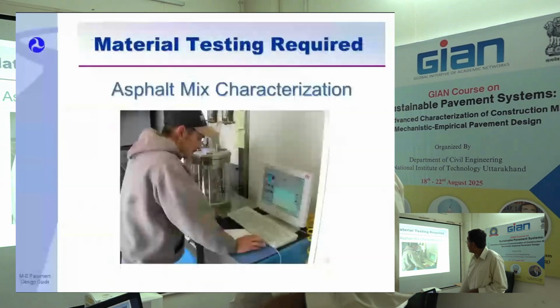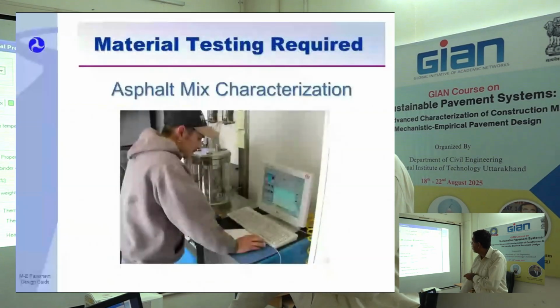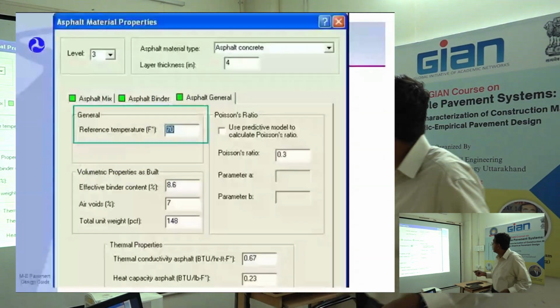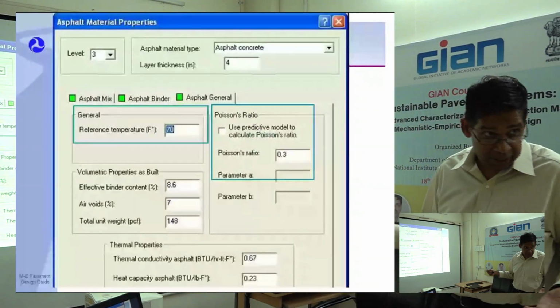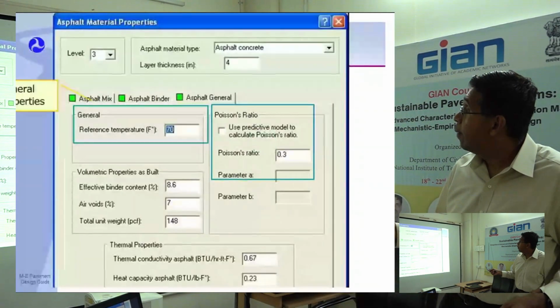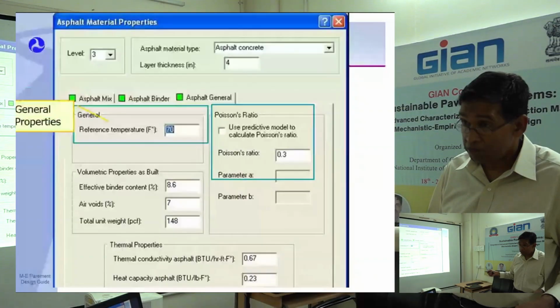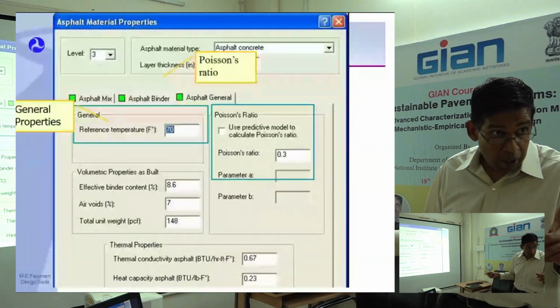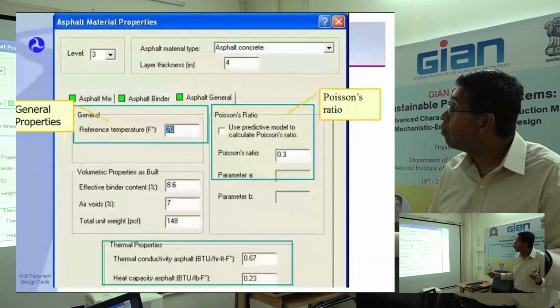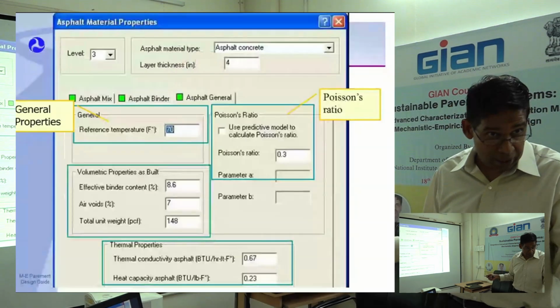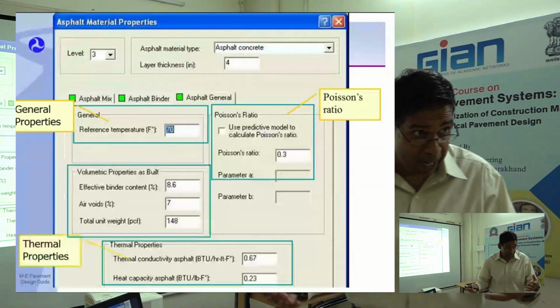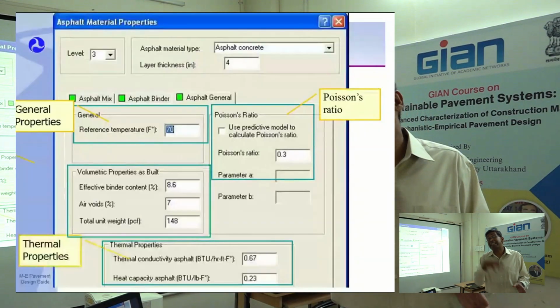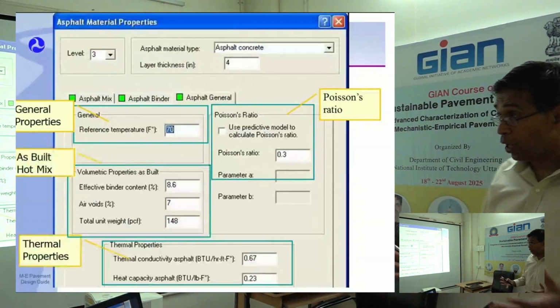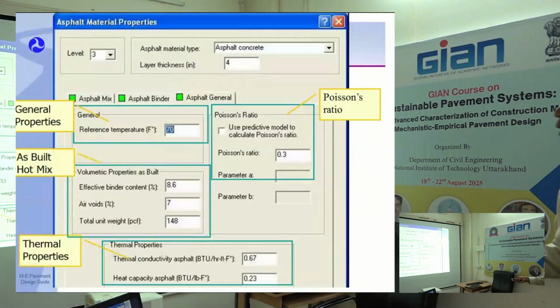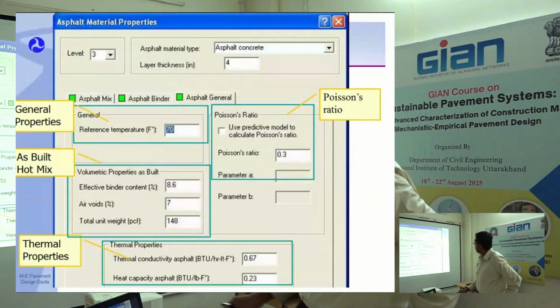Asphalt mix characterization, that's your dynamic modulus right there. Reference temperature 70, you can pick your own reference temperature. Binder content is by volume, not by weight. By volume, binder content is twice that by weight. So you are used to 5%, 5.5%, but by volume it becomes exactly double. So by volume it occupies twice the volume. And then you have the thermal conductivity. Why not?